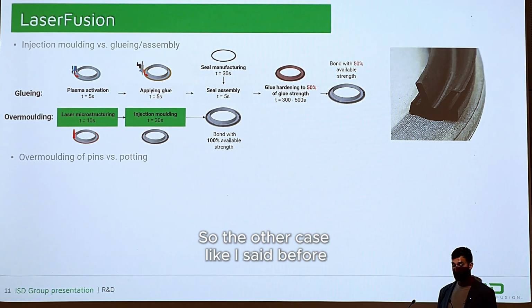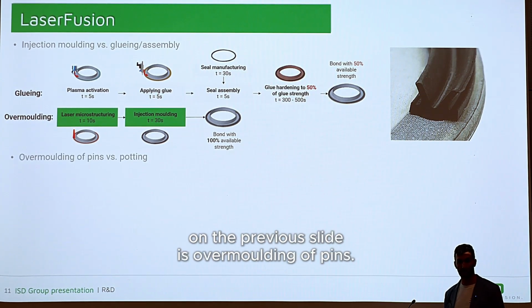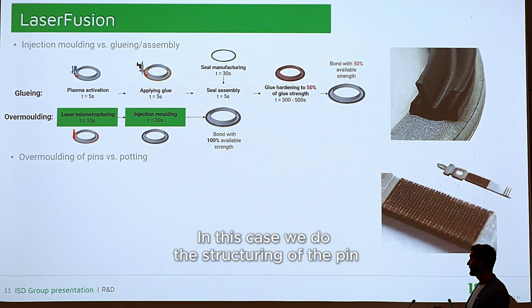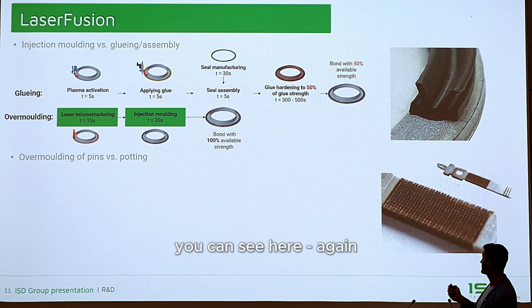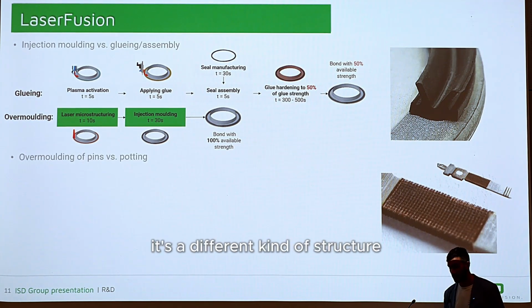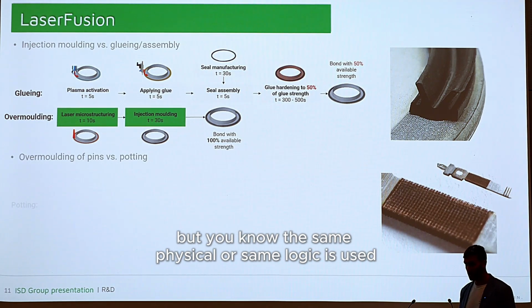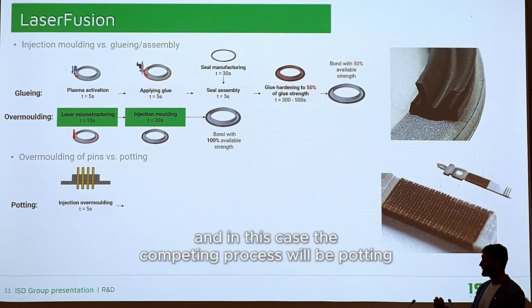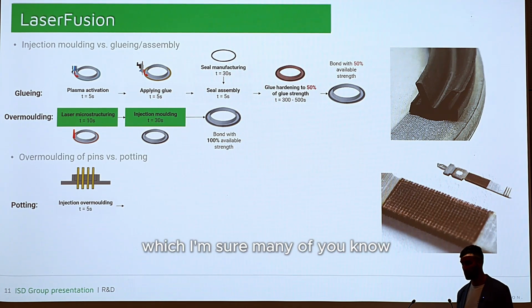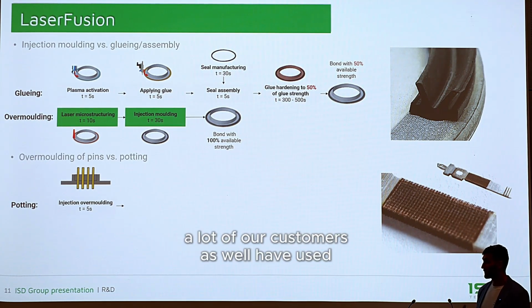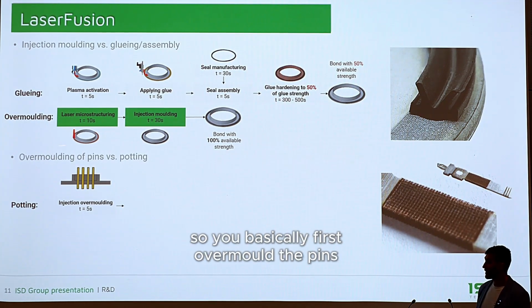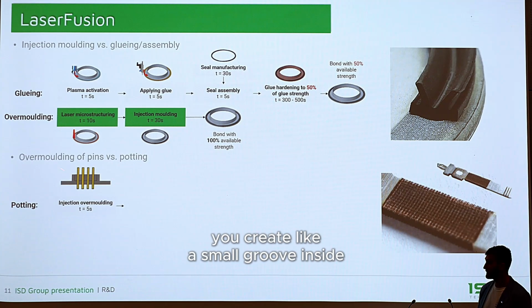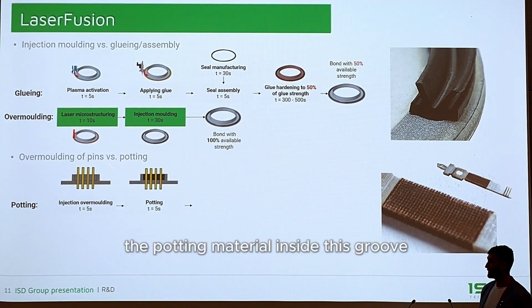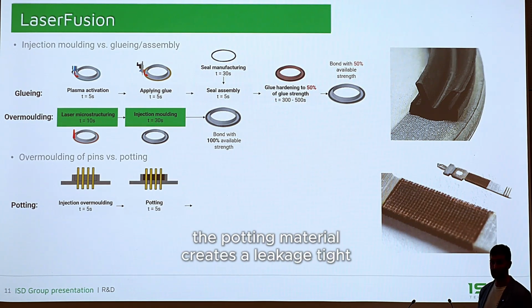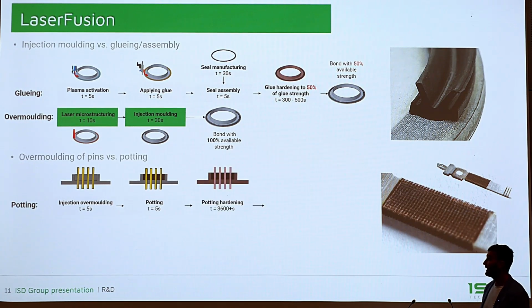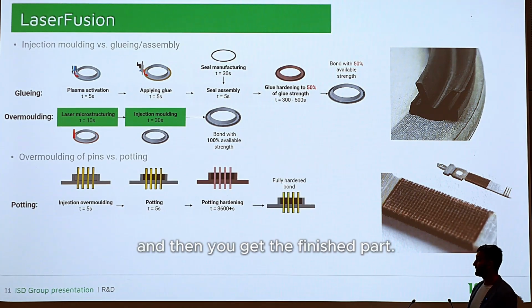The other case, like I said before on the previous slide, is overmolding of pins. In this case, we do the structuring of the pin, as you can see here. Again, it's a different kind of structure, but the same physical logic is used. And in this case, the competing process will be potting, which I'm sure many of you know. A lot of our customers have used or are still using potting. So you basically first overmold the pins, you create a small groove inside, and then you pour the potting material inside this groove. The potting material creates a leakage tight bond between the pins and the polymer matrix. And then you also need to harden it, and then you get a finished part.